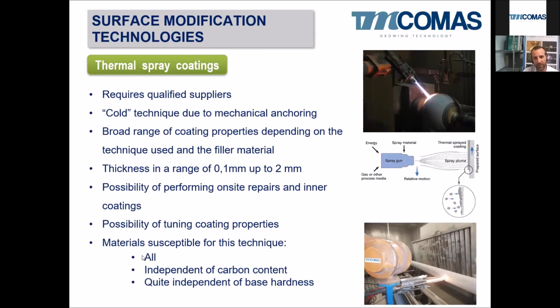One clear advantage of thermal spray coatings is that we can apply all these coatings virtually to all surfaces. So all base materials can be protected by thermal spray coatings. As we are not welding, weldability is not an important key for thermal spray coatings, and we can apply a coating onto copper, titanium, steel, glass, ceramics, carbon fibers, and so on. Very interesting applications.